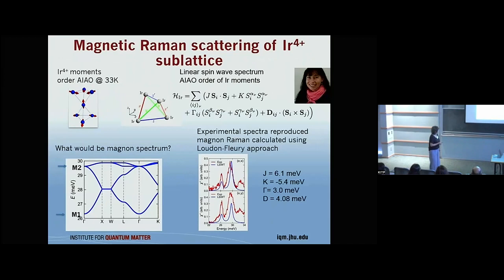The first step was to calculate the magnon spectrum of iridium. So iridium orders in all-in, all-out; we are pretty confident. So the magnetic band structure of all-in, all-out order will have three degenerate bands at higher frequencies and one degenerate band at low frequencies. Then they wrote this Hamiltonian, which includes all possible interactions between iridium atoms, and they used the values which fit our experimental spectrum. And so here are the values, and from the geometry of this order, they could predict polarization dependence.